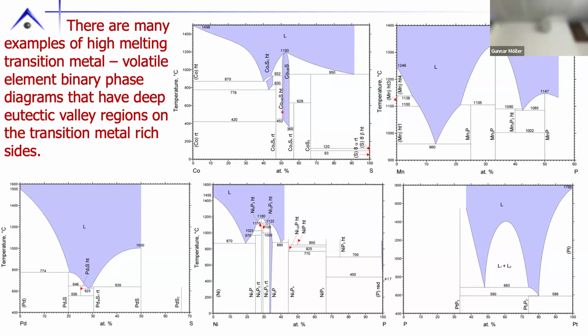So a eutectic, this is the eutectic point. It's the minimum in the liquid where I have liquid coexisting with two different solids. Okay, for me, it's important because it defines the lowest temperature I can take this and still have a liquid. Okay, this, by the way, is a peritectic, a decomposition of a material, just another term. All right.